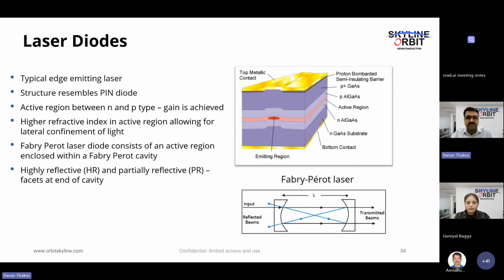They are basically the same as LEDs, but it is just that we can get lasing out of this active region. Because we can make quantum wells with nanometer level thickness, which can give quantum confinement, we can get lasing using this active region. So we can fabricate laser diodes. They are basically PIN diodes, and the gain is in the intrinsic region only. So it acts like a Fabry-Perot laser. You can see the shining part is there, top and bottom region. So the light is trapped between the two reflective regions, and the lasing happens through the side. Okay, so this is a very standard device.